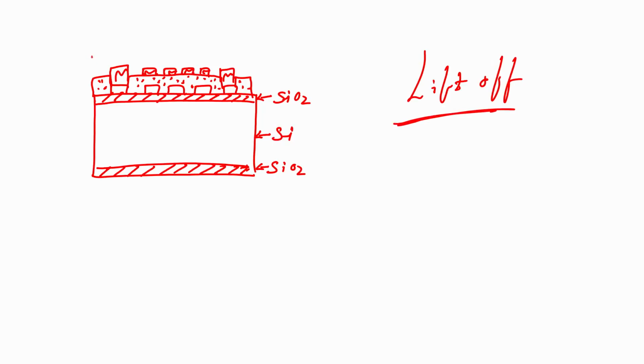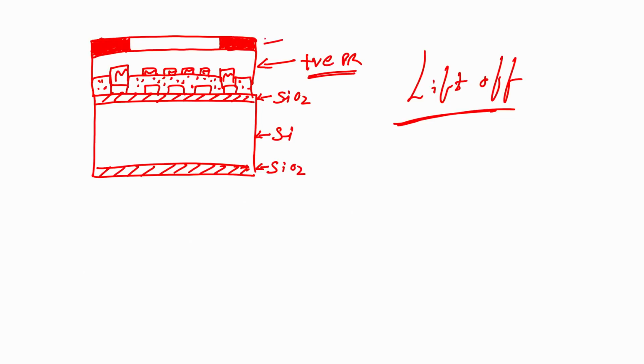So, instead of depositing piezoresistive material first, we will spin coat positive photoresist. Alright, we will spin coat positive photoresist. Then we will use a dark field mask. Of course, after positive photoresist spin coating, what is the next step? Next step is of course the soft bake. So, spin coating, soft bake at 90 degrees, 1 minute on a hot plate, we will load the dark field mask and I have positive photoresist. So, if I expose the dark field mask with UV, what will happen? The unexposed region will be stronger and the exposed region would be weaker.